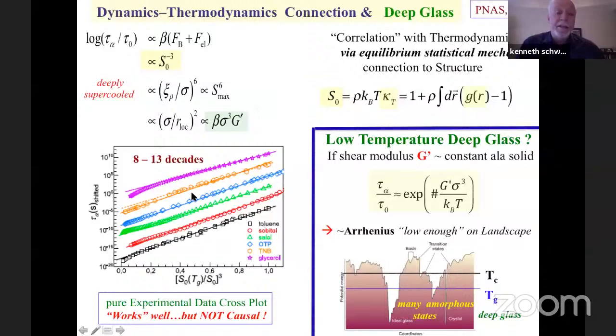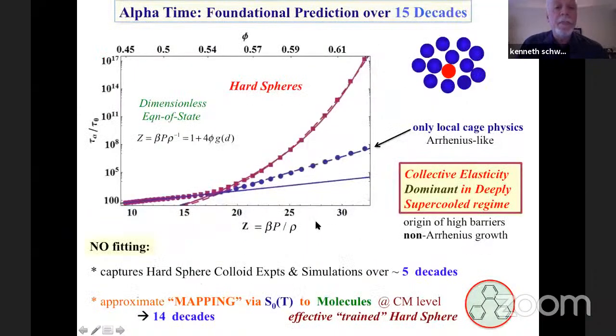We're not saying this proves that the glassy dynamics is controlled by thermodynamics. In fact, we're saying just the opposite. If we go to the low temperature, deep glass regime, then we can't trust this connection to thermodynamics there. We don't know much about the thermodynamics. We're using integral equation theory to determine the input to the theory. But we can use this connection that predicts the alpha time grows exponentially with a shear modulus over kT times a number. And so if you're at low temperatures near the bottom of the landscape, it's entirely reasonable to imagine that the shear modulus is almost constant. And if it's true, then the theory would predict a low temperature crossover to an Arrhenius behavior. And I think Greg McKenna will discuss this phenomenon from his perspective. Okay, now I want to only very briefly say something about older things in the literature.